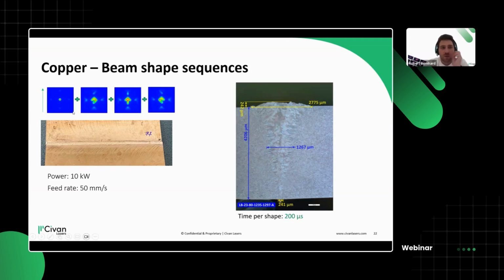How do we do that? For copper, we need high intensity to just get the process started, and we can do this very well by doing constructive interference in a single point. So this is an interference point. You see it's really small, condensed, around 85 micron in diameter. But then I switch every 200 microseconds to a different shape, kind of an arrow shape, but with a stir bar at the end. That's the idea. The top again is the leading edge, and by welding this way, at high speed, we are keeping the keyhole open for longer. We are avoiding collapses, and by distributing the heat, we also avoid overheating the material itself. So there's no spatter, no melt pool explosions happening.